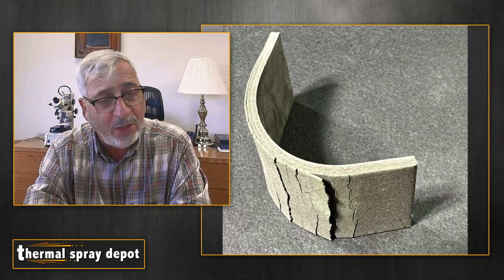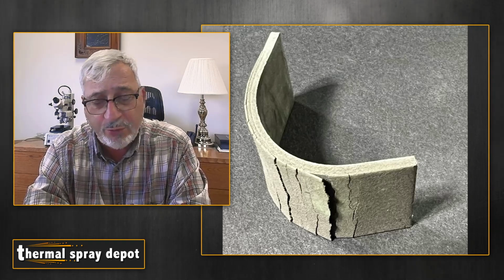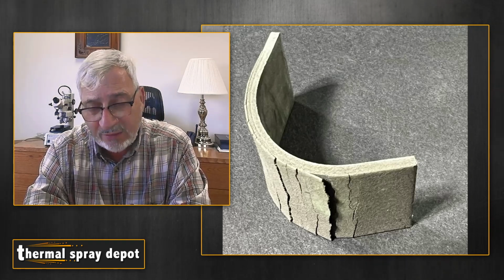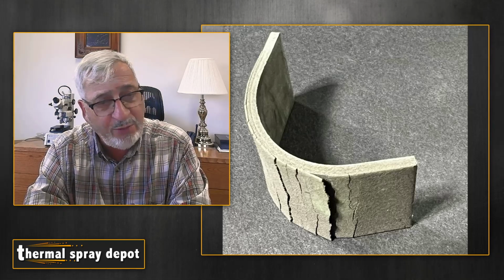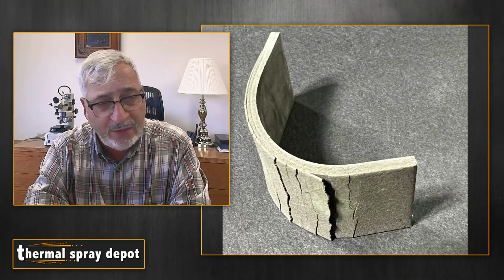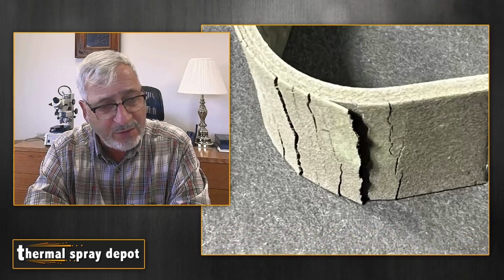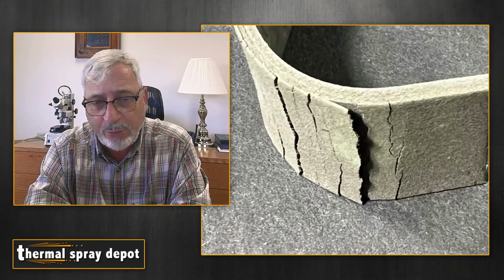This was a demonstration to the operators on how, if you have bad surface prep, the coating will not stick. So on a pretty large radius bend, the coating is popping off, and you can see that it's just totally separating and coming off. Similar to what you saw in that bridge picture earlier where the paint was coming off. In this case, our thermal spray coating is coming off. We don't want that to happen.